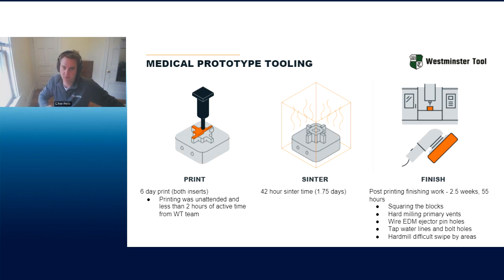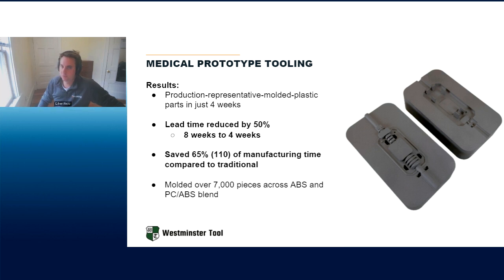But ultimately what the result was, they were able to deliver production representative molded plastic parts to their medical OEM customer in just 4 weeks. This was a 50% lead time reduction, down from 8 weeks down to 4 weeks. They saved 110 hours of active manufacturing time compared to traditional manufacturing, and they delivered to their customer over 7,000 pieces of ABS and a PC ABS blend for that medical customer to do their biocompatibility testing.